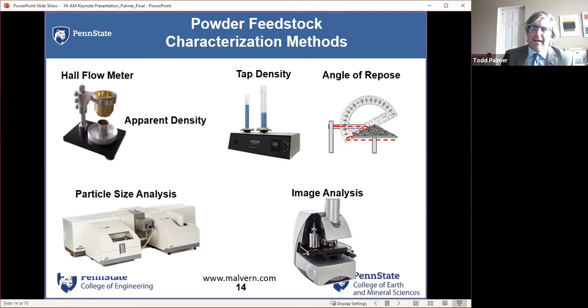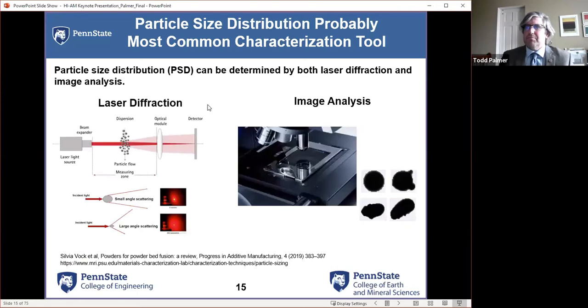That doesn't really reflect what we see in powder-based additive manufacturing, where we're taking a blade and basically skimming and making a powder layer, or flowing powder through nozzles. So particle size distribution is the first place we start. It's a fairly common test, pretty simple. We can use laser diffraction techniques where we disperse a powder in there and look at small angle and large angle scattering. We get an idea of what the distribution of particle sizes is.